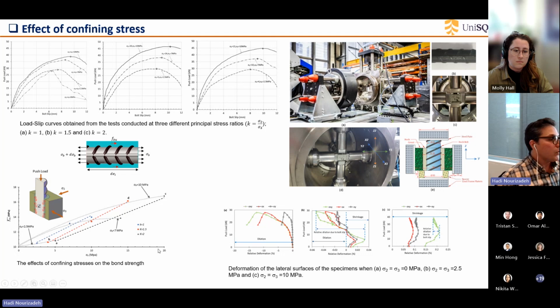We have sigma 2 on the horizontal axis and the bond stress or strength on the vertical axis. At a specific sigma 2, we realize that by increasing the principal stress ratio, the bond stress or strength decreases. Also, interestingly, at a specific sigma 3, for example 10 MPa, when we increase sigma 2, we see a plateau here. This is very important. Why? Because it shows that, for example, when in an underground we have 50 MPa or 60 MPa of stress, which is really high, we shouldn't expect higher bonding strengths.